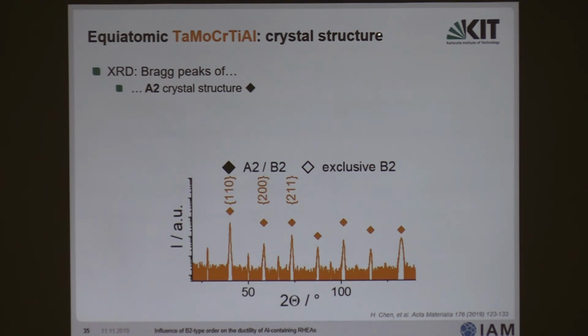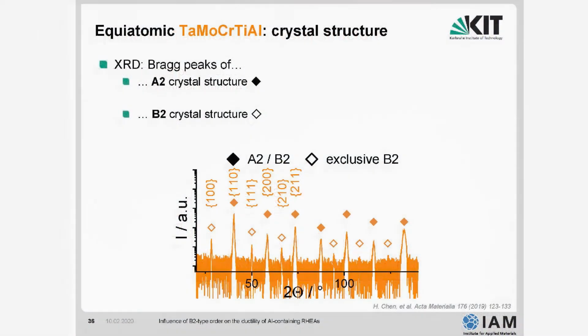Now, is this really an A2, meaning a disordered solid solution, crystal structure? No, it's not. As you see here, you have tiny little reflections here and there. Somehow the signs got lost. Here you have some indications of B2 structure. So we do have B2 lattice superlattice reflections, meaning we do not have a random distribution of atoms, but some of the atoms take one atomic site and other atoms take another atomic site, preferentially.